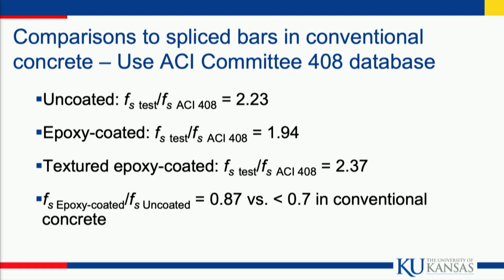The textured coated epoxy, if you notice, the ratio came out to be even a little bit stronger than the uncoated bars. That tells us that texture-coated bars are giving us at least the same strength as the uncoated bars. And by the way, all these comparisons are at the same compressive strength for both the conventional bars in ACI and the test bars we have here.